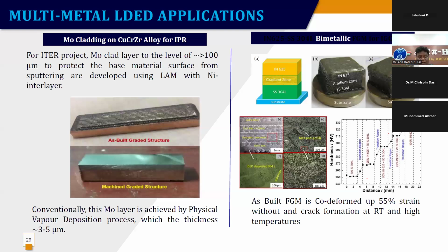Then people tried to work on using PVD, physical vapor deposition. Even CVD was tried out, but again the thickness was limited to 3 to 5 micron, and here we are talking of something more than 100 micron. One good thing that I want to tell here is that deposition of moly on copper was not possible. So what we did is, we introduced a nickel interlayer. So you have copper, then we deposited nickel over it, and then we deposited moly on this, and moly and nickel are good, and copper and nickel are good, and introducing this interlayer made our life very simple.